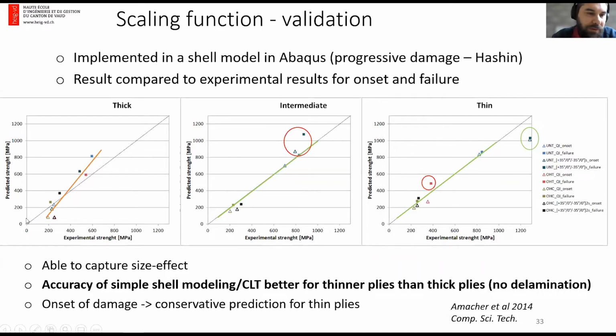And we can see here that for the prediction in the thick ply, actually, the models don't match very well with reality because a shell model does not account for delamination. And while we reduce the ply thickness, we can see that the simple shell models are actually more efficient at predicting the performance for thin ply than they are for thick ply. So that's a good sign because it means that you can use classical laminate theory or shell modeling more accurately with thin ply than for thick plies, just because there's no delamination.